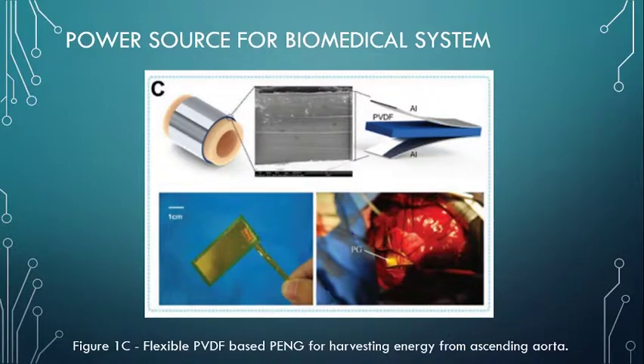When the PENG was implanted in vivo by wrapping around the ascending aorta of a porcine, the max voltage of the implanted PENG was 1.5 volts under a heart rate of 120 beats per minute and a blood pressure of 160 over 105 millimeters of mercury. The instantaneous output power could reach up to 30 nanowatts with a long-lasting duration of 700 microseconds and 77.8% duty ratio. The implanted PENG could charge a 1 microfarad capacitor to 1 volt within 40 seconds.